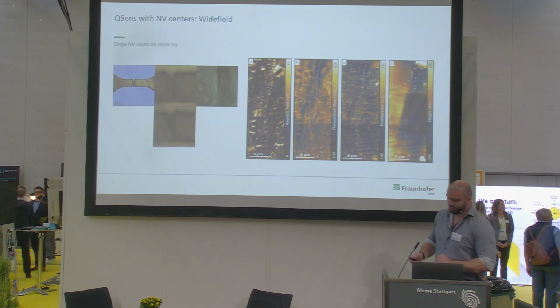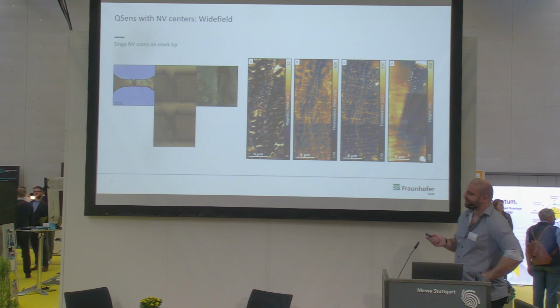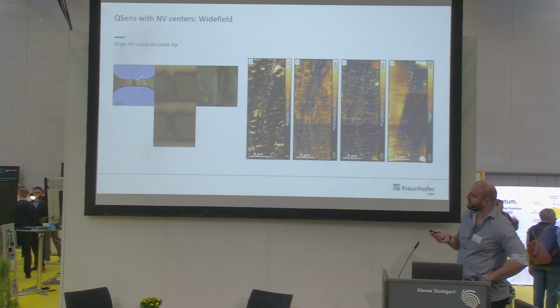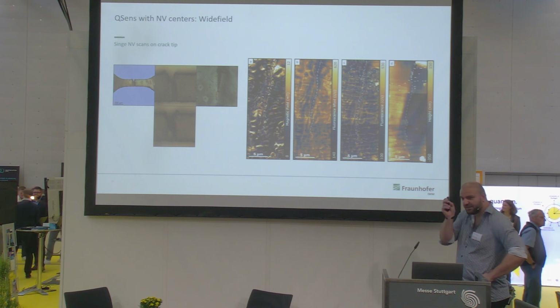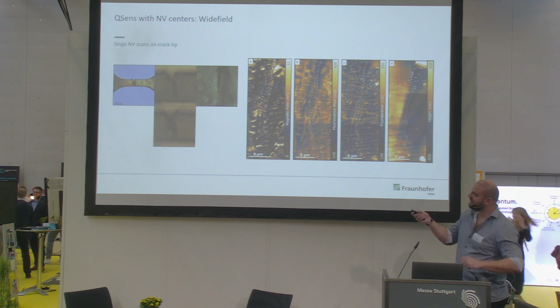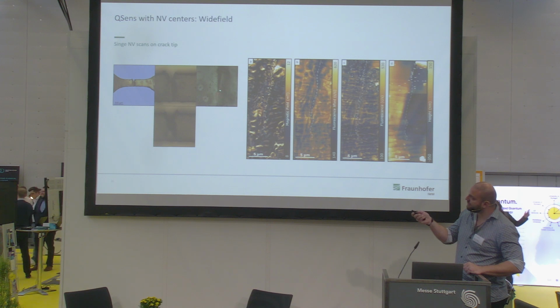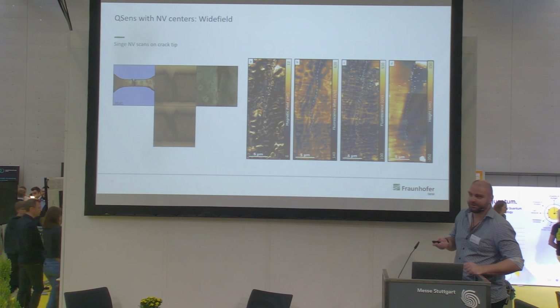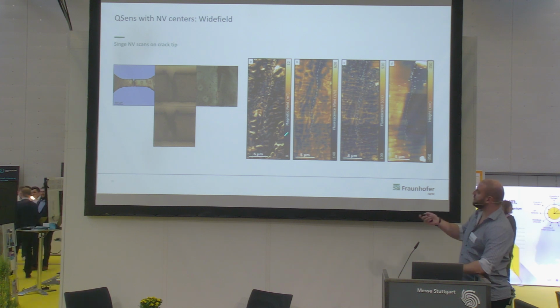So what we did, we have our tensile sample, and we fabricated a crack here on the side. So we did a small slash with a razor blade, then we fatigued, and then there's the crack evolving. And here on the very tip of this macroscopic part, there's a micro crack happening, which we don't see here. So now we go to the scanning system, and we scan over this red area here.